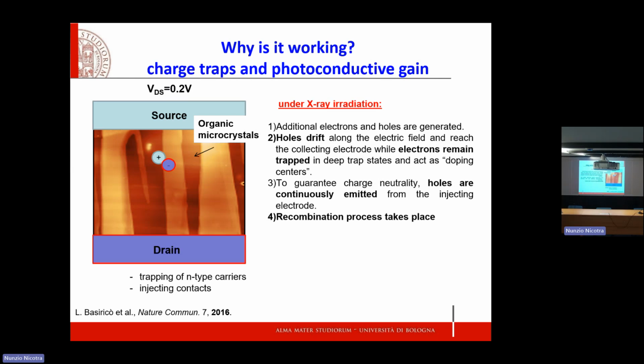So the impinging X-ray photon arrives, creates an electron hole pair, not many, but those that are created are trapped at the defects that are present at the surface of my microcrystalline material. And therefore, the more electrons get trapped, the more my material needs to maintain charge neutrality, absorbing or attracting carriers from the injecting electrode. So to maintain charge neutrality, more and more carriers are sent through the electrodes. And that is a process that allows such materials to increase the collected current up to 10 to the 6th. This is happening because the trapped charges stay trapped for a very long time. So the lifetime of these electrically active defects is very long.